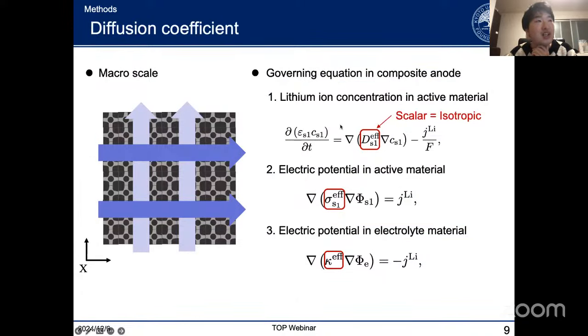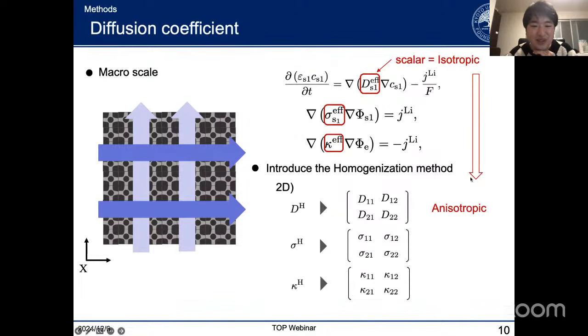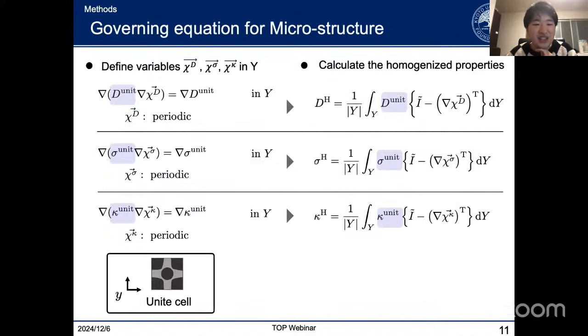Following the conventional topology optimization method, we relate the effective material property to the design variable rho. We pick up the diffusion term, which is now a scalar, but using the homogenization method, we treat this term as a tensor, so we consider it anisotropic. I explain how to derive this term. This is very simple. In the unit cell, we solve the characteristic governing equation, and by using this, we can calculate the homogenized diffusion coefficient.